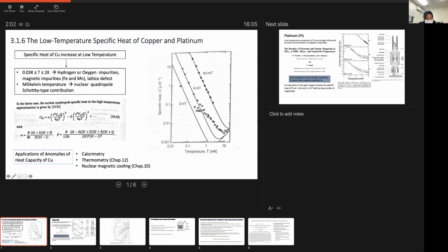Basically it's similar to the magnetic specific heat, right? Yes, the Schottky anomaly. This quadrupole interaction makes split energy states, for the free spin, I mean impurity spin, that makes a low temperature Schottky-like specific heat. This is related to the nuclear magnetic specific heat at low temperature.